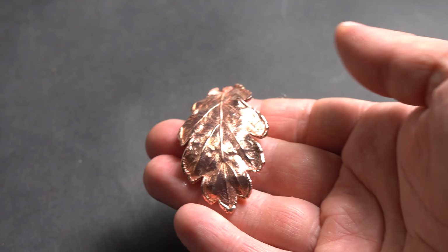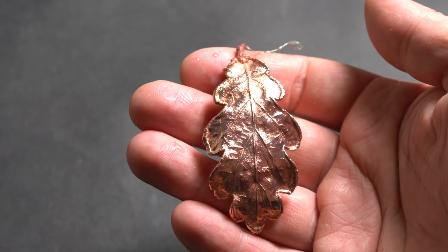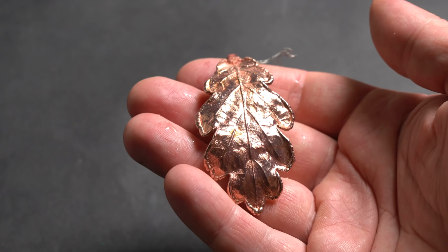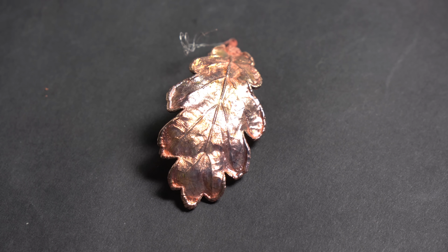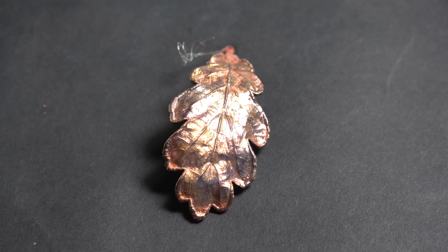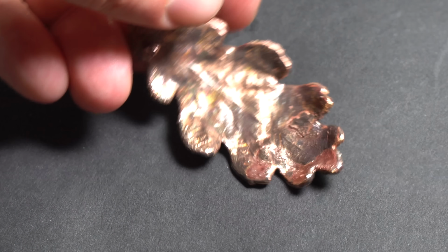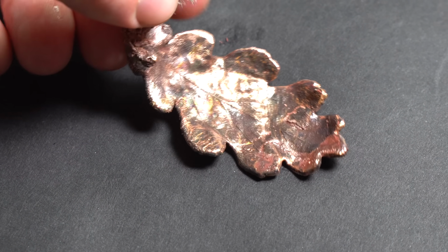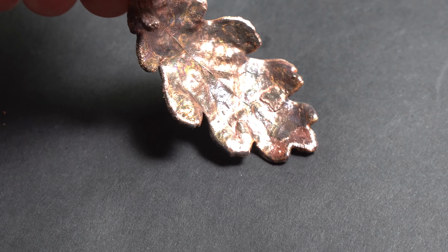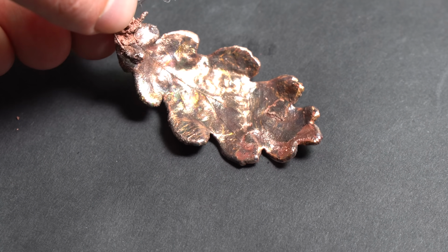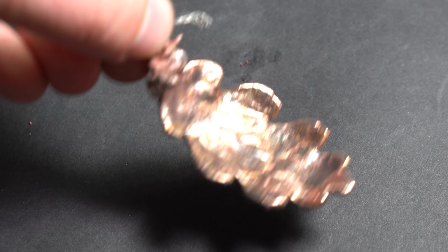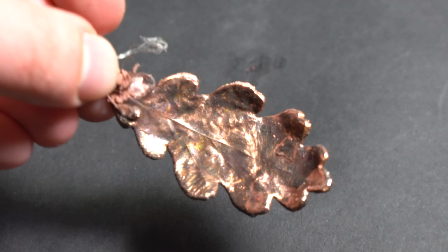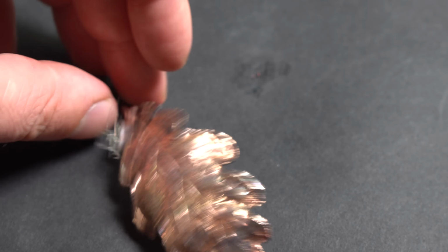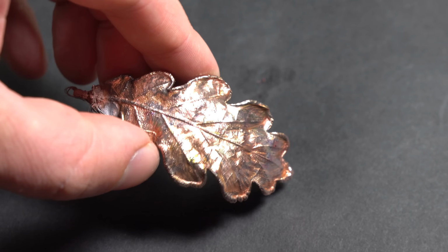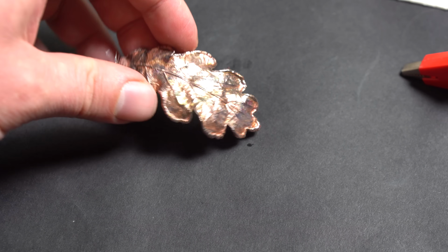When exposed to the air, however, this leaf quickly started oxidizing because of a large surface area and also because copper crystals in this layer are too small. That is why this shiny copper layer immediately needs to be covered in a protective layer of nickel in order for the copper not to fade and oxidize. Besides, the copper layer is quite fragile, which is why this copper leaf can easily break.